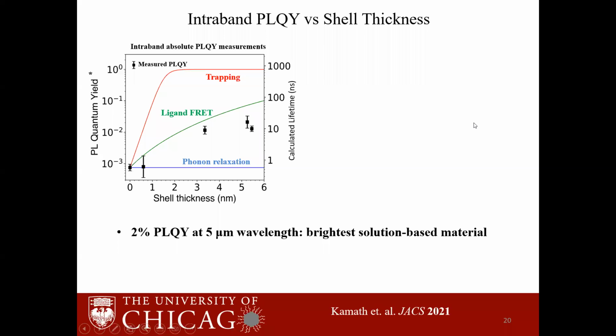We can see that growth of the thick shell leads to a drastic increase in the quantum yield. While the initial cores have a quantum yield of few times 10 to the minus 4, the thickest shells have a quantum yield of 2%. Now, as Philippe said, 2% does not seem like a lot, but at 5 micron wavelength, this is the brightest reported quantum dot for any solution-based material.